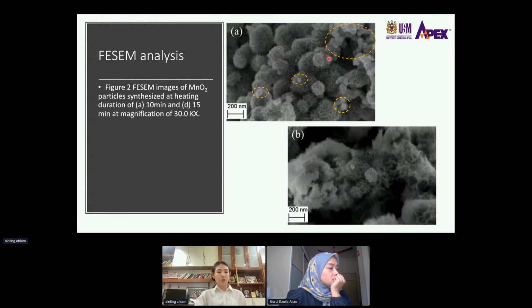Here are the morphologies of the manganese oxide particles synthesized at 10 minutes and 15 minutes. In general, they possess different morphologies. At 10 minutes, we can see that a hierarchical flower-like structure was formed. When we look closer, we can see that these flower-like particles were made up of an assembly of thin intersected nanosheets. Besides, we can also observe some tiny particles deposited on the MnO2 nanoflower, as highlighted in yellow. By increasing the heating duration to 15 minutes, an agglomerated structure was observed over the surface of the MnO2 nanoflowers.